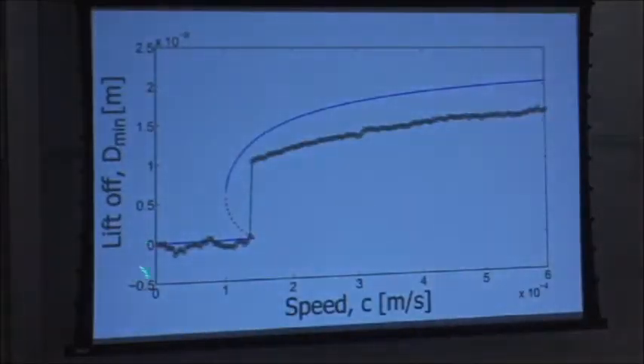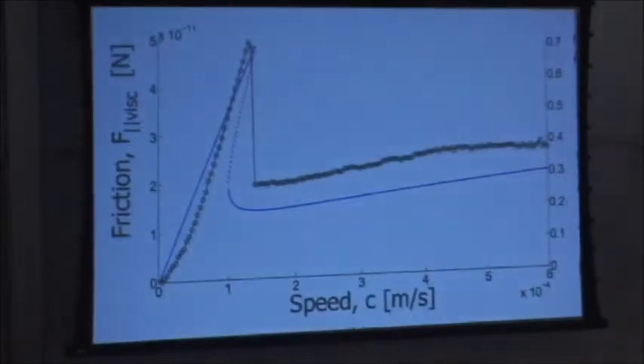And here's the data directly. This is the experimental data. The tip is only lifting off a nanometer, so this took a long time to record. The thing is moving at up to 5 millimeters per second there, and we get this discontinuous jump. It doesn't just move off gently, it jumps. And if you look at the theory, it's bistable. When you get to this point, it will jump because of this bistability in the plot. It's not matching exactly, but you can see essentially it should go here and then jump and then continue. So the tip is lifting off the surface if you go fast enough. That's why it worked. We went fast enough just by chance, and we got that result. And then you can look at the friction, similarly at about 1 millimeter per second. Again, a bistability in the friction.